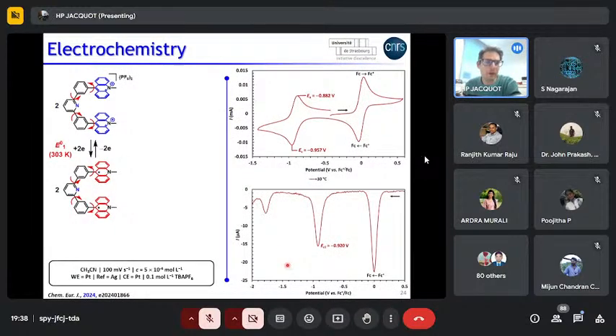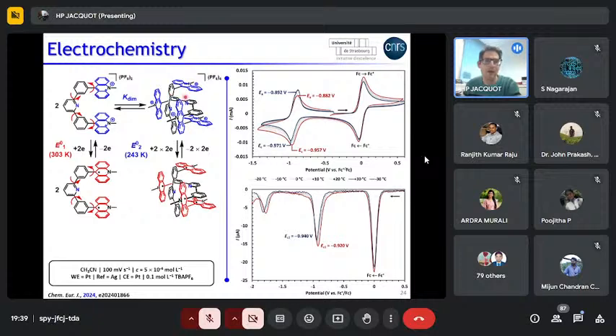So what we know is that at, let's say, roughly high temperature, 30 Celsius, we have only the monomer. So if you look at the electrochemistry, we have one reduction peak, which is the peak of the monomer. The other peak is just a reference, which is commonly used in electrochemistry, which is ferrocene. Then also what we know is that when you cool down the temperature, you will form the dimer, and you see that you have a shift of the reduction potential towards more negative values. So this new potential that you can assess is the potential of the dimer.